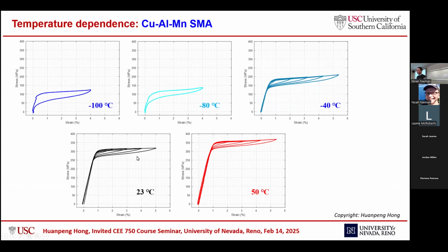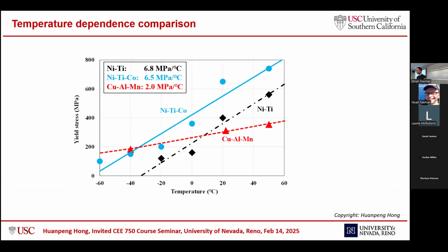What is really impressive is that I tried to lower the temperature to minus 100 Celsius. This exceeds the temperature range on Earth, but this material still exhibits almost 100% strain recovery. So this indicates the great potential of this material for deep space applications.